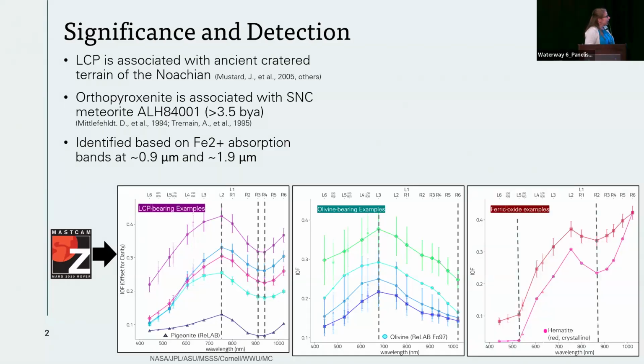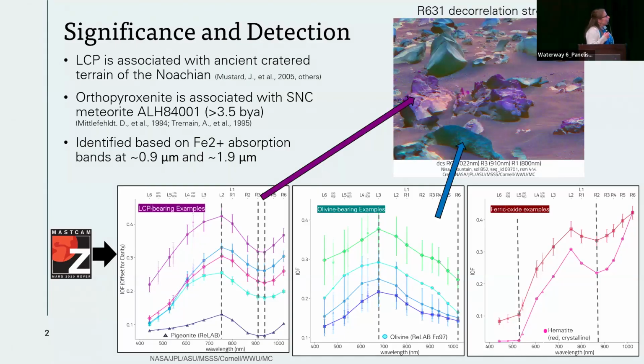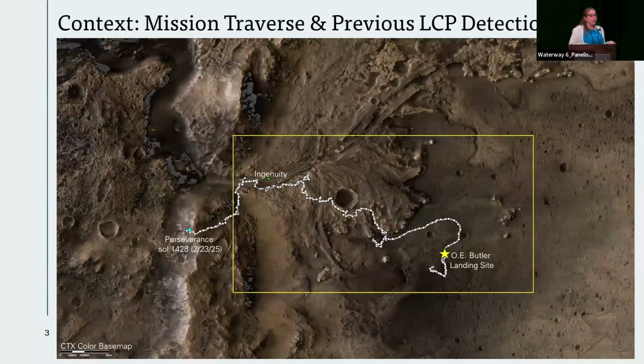That's what that looks like in our data set, and from ferric oxide materials that have the 528 nanometer band, and especially with hematite, a shorter wavelength of absorption just below 900. And then nicely, when we use these wavelengths in our decorrelation stretch images, things that have a 900 nanometer band tend to show up as purple. Things that have a 1 micron band tend to show up as blue, which is a helpful guide for us as we go along.